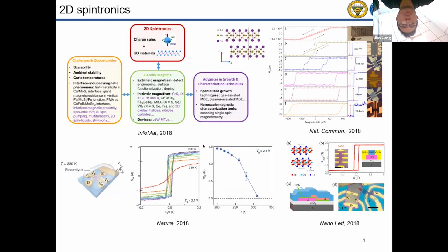In research of spintronics, the key point is that FGT has good electrical conductivity, and it has strong out-of-plane magnetic anisotropy and is a hard magnetic metal. The coercive force can reach 5,500 Oersted in nanoflake. In bulk FGT, the Curie temperature is 230 Kelvin. In monolayer, it can reach 130 Kelvin.